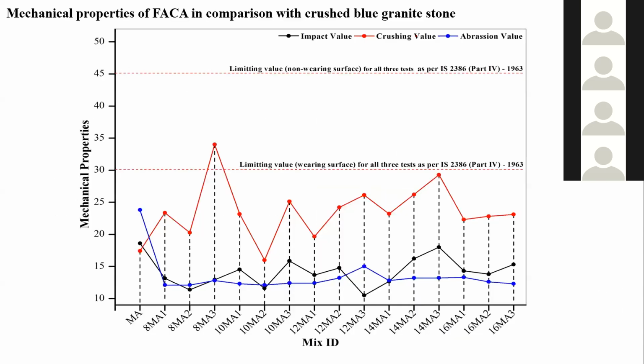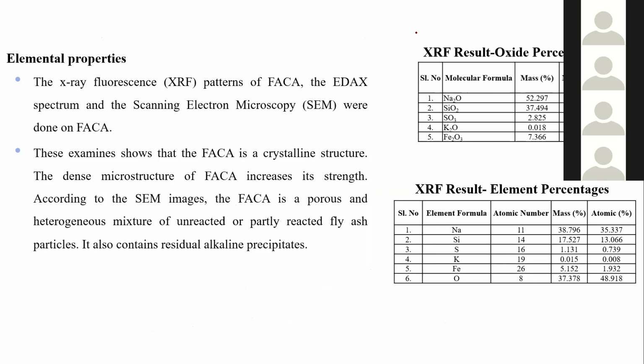One more thing, if any material comes to the market, people ask about the chemical composition of this aggregate. We did SEM and XRD, XRF also. From the XRF result, we can obtain the oxide percentages: how much Na2O, SiO2, SO3, K2O and Fe2O3 oxide compounds we can calculate from XRF. The element percentages, atomic numbers and masses are more or less equal to the conventional aggregate. That is what we can obtain from the study.